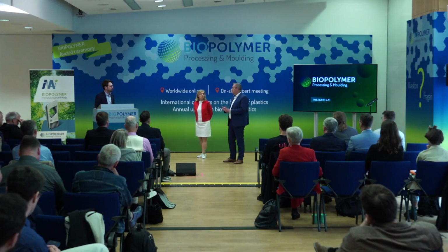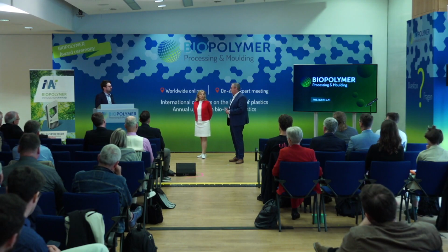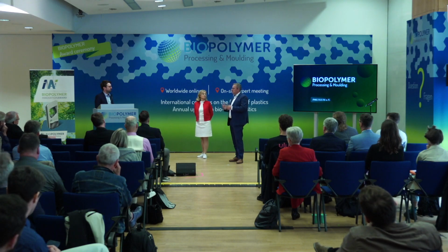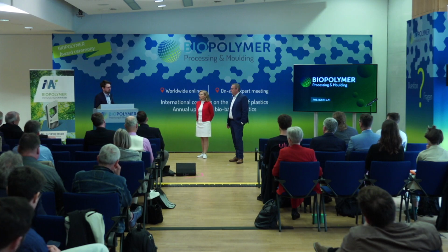Okay, thank you. How is the impact on coloring? Is it getting more whitish since the MFC looks white? Is there any shift in colors? Can you comment on that? What we saw is that when we evenly and finely distribute those fibers in the binder system, then we talk about a translucent material where the fibers are hardly visible, more or less. So you can pretty much color it in every color. There is probably an off-shade when we talk about 10 to 20% MFC, but most of the applications which we see are restricted to 1 to 5% of MFC incorporated into the binder system.